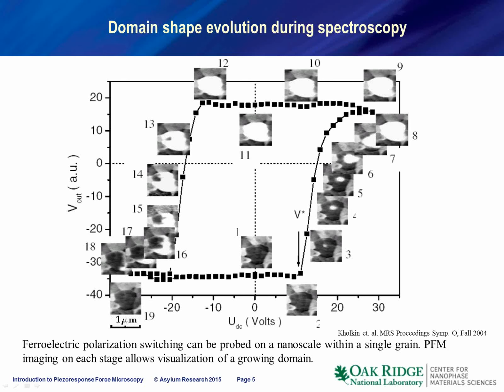Now, let's look at the picture of how this domain switching happens. This slide illustrates a very detailed and very careful study by Andrei Kholkin, who imaged ferroelectric domains at each point of the switching process. This is an extremely time-consuming experiment, and as far as I know, it was basically done only once. But it illustrates the relevant aspects of the polarization switching.